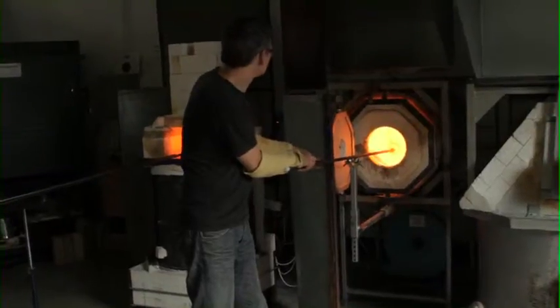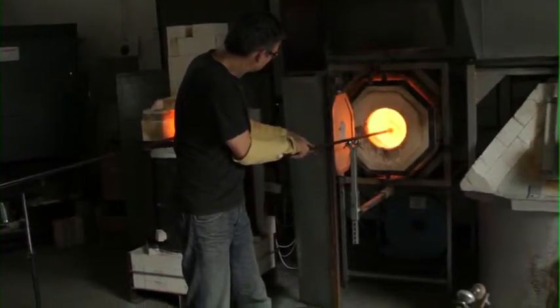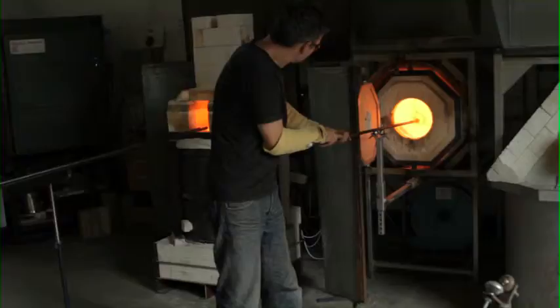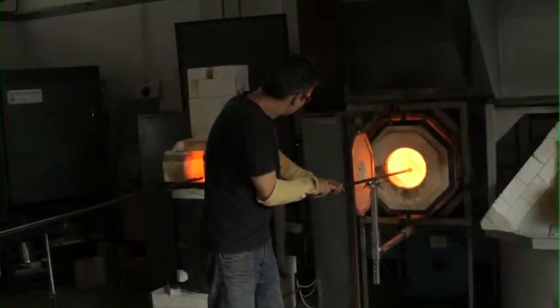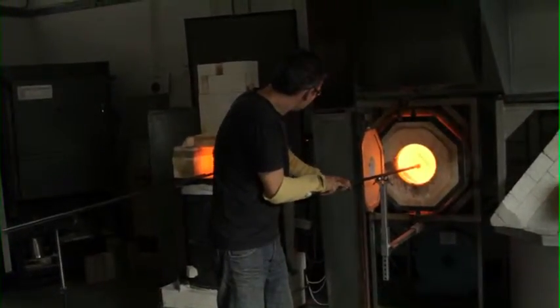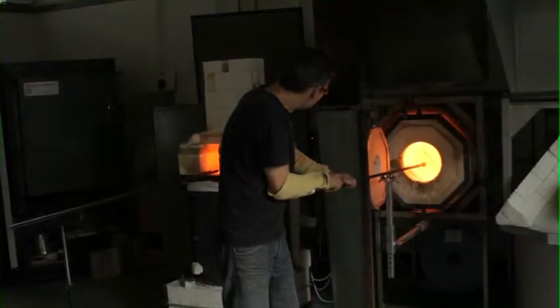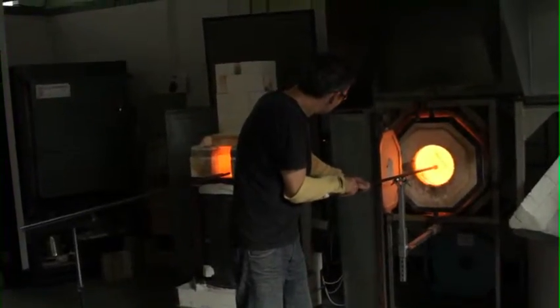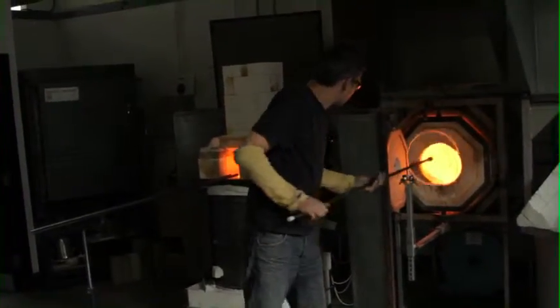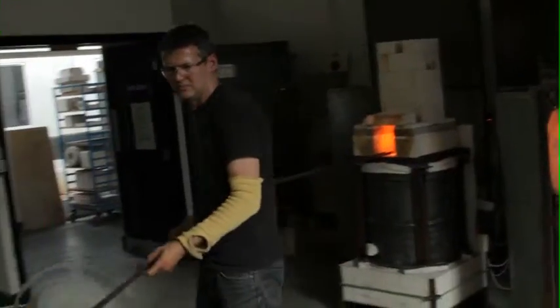It implies a viscosity curve greater than any glass I've ever worked with before. If the working temperature is so high, the annealing temperature should be quite high too, certainly above 500 degrees C. It seems that the window of workability could be as great, if not greater, than that of lead crystal.